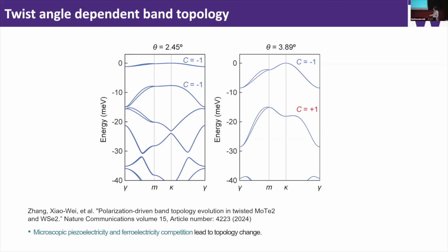He's going to tell you why the sign of the Chern number will change as a function of twist angle. But in a nutshell, from the experimental point of view, in these twisted TMD systems, there are two polarizations coming into play. The first one is a charge transfer from one layer to the other layer. This gives you a dipole in the vertical direction, which contributes to the moiré potentials. At the same time, there's a strong lattice relaxation. This lattice relaxation gives you an in-plane strain gradient, which gives you piezoelectric polarization. That also contributes to the moiré potentials. Then this in-plane piezoelectric polarization will compete with the out-of-plane electric dipoles.